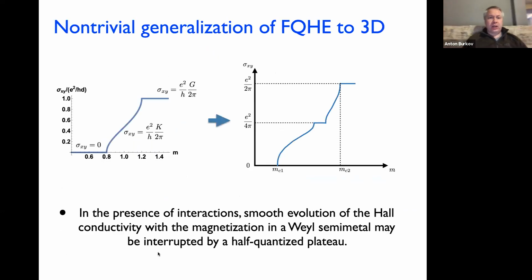So basically what we predict is the following. In a non-interacting or weakly interacting Weyl semimetal, I have the following picture, right? As I change the magnetization, I'm going to have this smooth transition from an ordinary insulator with sigma xy equals 0 to an integer quantum Hall insulator with sigma xy proportional to the reciprocal lattice vector. So with strong interactions, we predict that there can be a plateau in this smooth dependence where the Hall conductivity is quantized to exactly half this value, to exactly half this integer value.